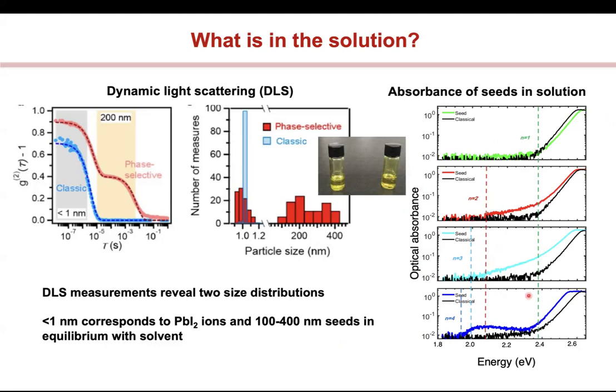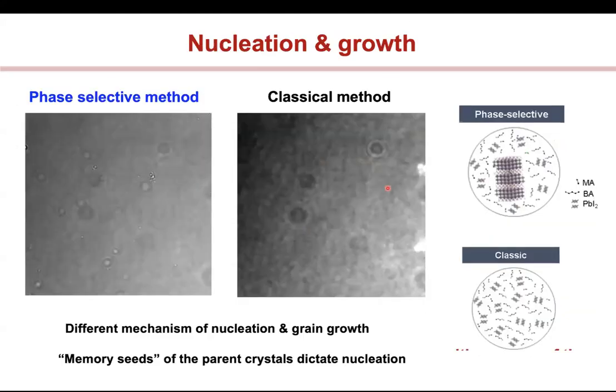If I showed you, that's what it matches, which told us that not only are these crystallites present, but they retain the electronic properties, the optical properties and the electronic properties of the crystals that you have added. And so that's where we coined the term that somehow they retain the memory of what the parent crystal is. And so we call them these memory seeds. Okay. And in fact, they have also very different nucleation behavior.